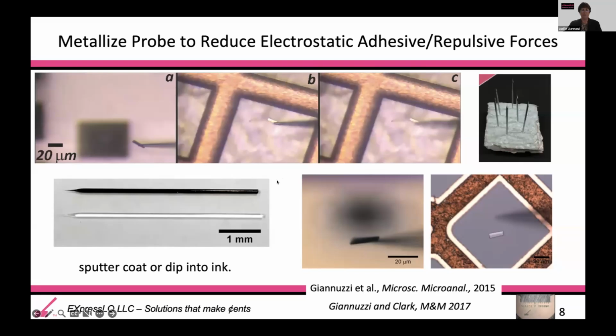a carbon-coated TEM grid. There's a number of reasons why we use glass tips instead of, for example, tungsten tips, which are already, of course, metal and conducting. The main reason is because if anybody has done in situ lift out and has accidentally doinked the tip onto the specimen, you know that those tungsten probes are extremely ductile and they will just curl up like a little elf shoe.